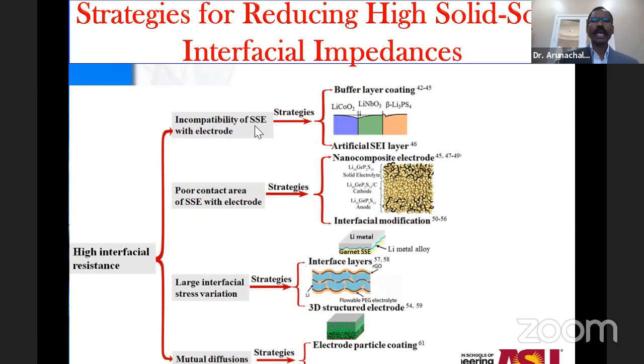So the strategy in handling the incompatibility is by using buffer layer coating. Between anode and cathode, you can have lithium niobium oxide or lithium phosphorus sulfide. So there are many possibilities. That's actually for sulfur electrodes. In other words, you can have an artificial SEI layer, solid electrolyte interphase layer.